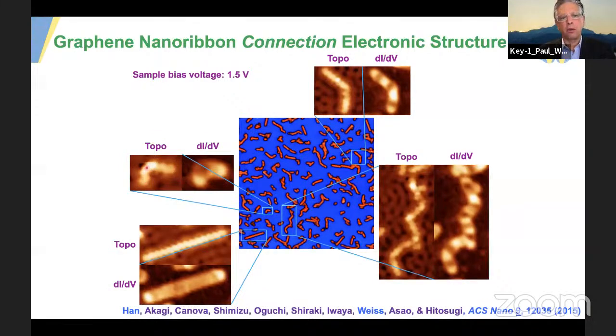If we just look at the conventional STM image, the topography, this junction looks like it may be a good contact. But in fact, if we look at the phase by measuring the differential conductance, we show there's a node, and that's a bad contact. And so if we go over here to all these stripes, that's the kind of thing that gives me nightmares. And that's not what we'd want for contacts.